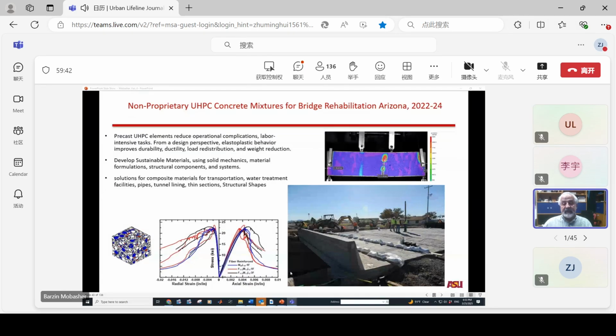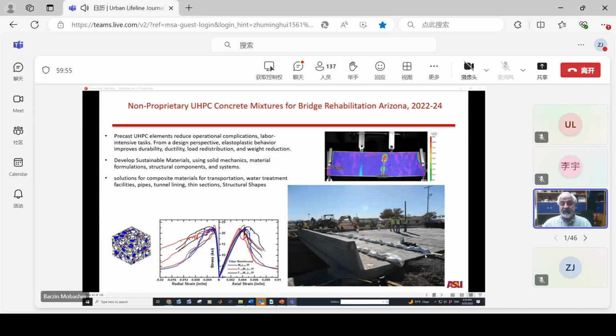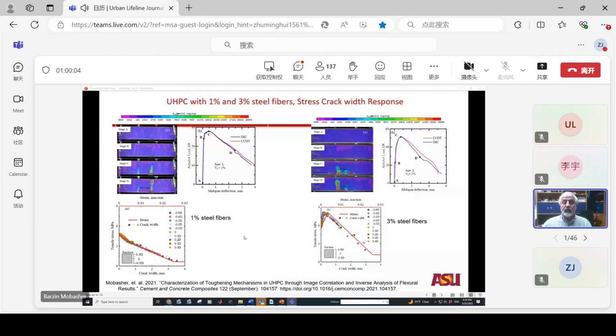So we have been looking at these tests for non-proprietary UHPC mixtures for bridge rehabilitation. What you see here is the bridge that we replaced in a matter of a week with precast sections, and we poured the connection pour with UHPC. So here is a test method that we did to calculate the load deflection result of the UHPC and back calculate the properties. I've written the DOI for all of the papers that I'm citing here.